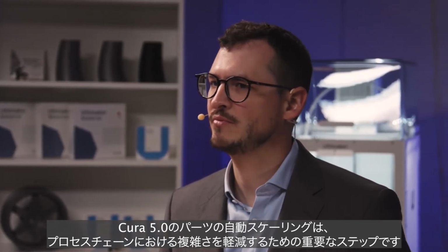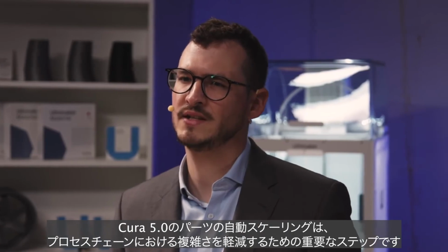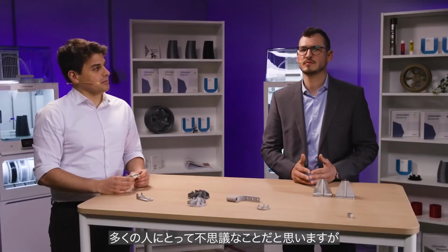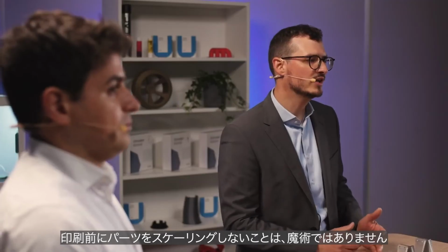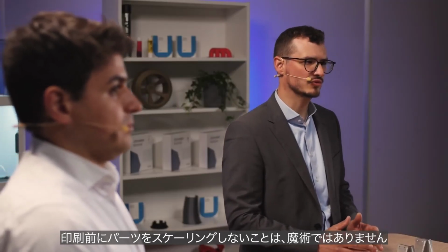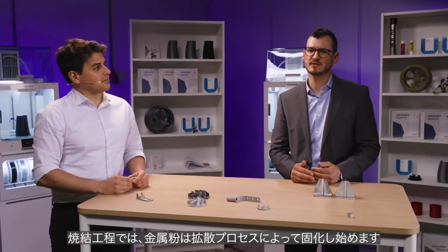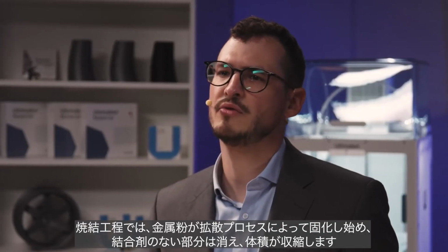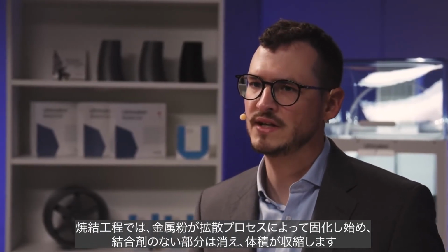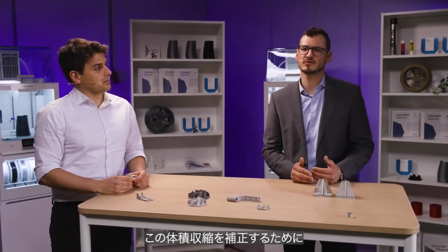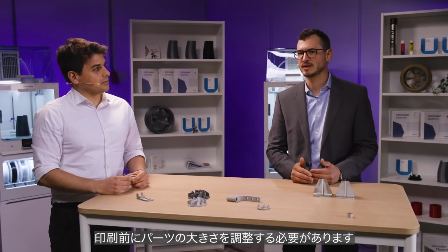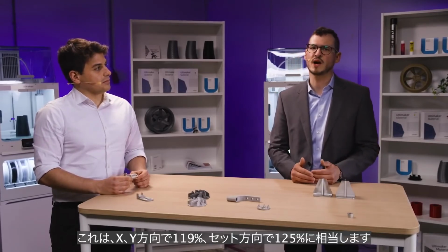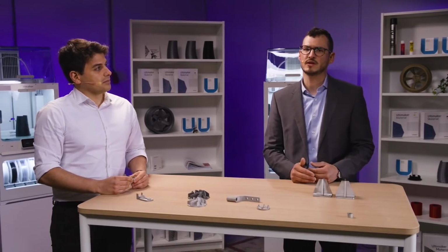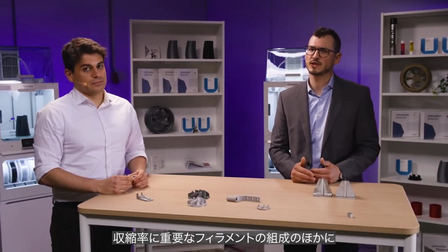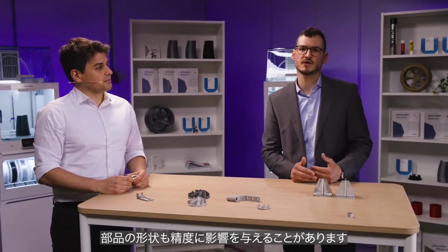Yeah, let me explain this to you. The new automatic scaling of the parts in Cura 5.0 is an important step towards the reduction of complexity along the process chain. I know it seems to be mysterious for quite a lot of people, but I can tell you scaling the part prior to printing is not witchcraft. During the sintering process, the metal powder starts to solidify by diffusional processes. The empty areas of the former binder vanish and the volume contracts, leading to a shrinkage. To compensate for this volumetric contraction, the parts need to be scaled prior to printing. This corresponds to 119% in X and Y and 125% in the Z direction. Besides the filament composition, which is critical for the shrinkage, also the part geometry can have an influence on the accuracy.